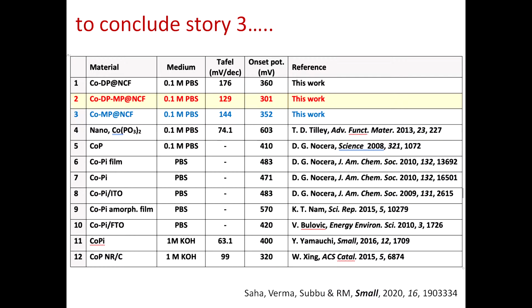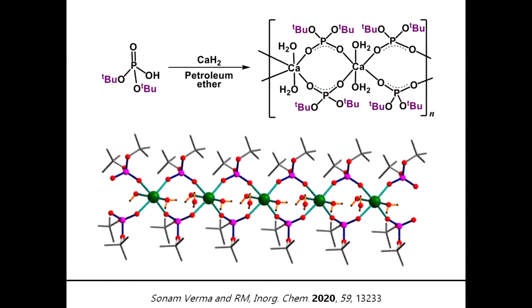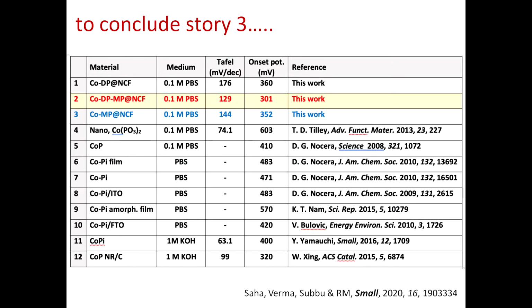So this is Dan Nocera's work where he has shown at 600 millivolts, I'm sorry, the onset potential for nano Co(PO3)2. So this 301, I think, probably was at that point of time a record for a cobalt phosphate material, which is the dihydrogen phosphate metaphosphate. Okay, and as you can see, this is the most famous work of Daniel Nocera, which was about 100 millivolts still higher than what we would report, because we are 10 years anyway behind. That doesn't really matter. Okay, so I'm just going to leave it at that at this point.